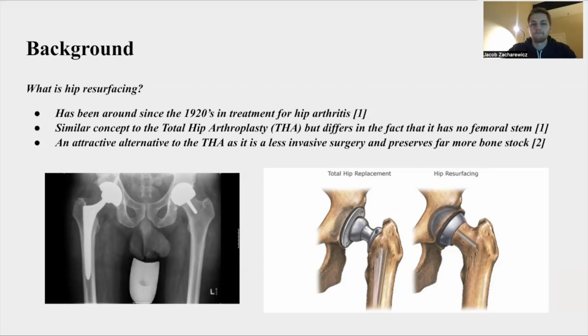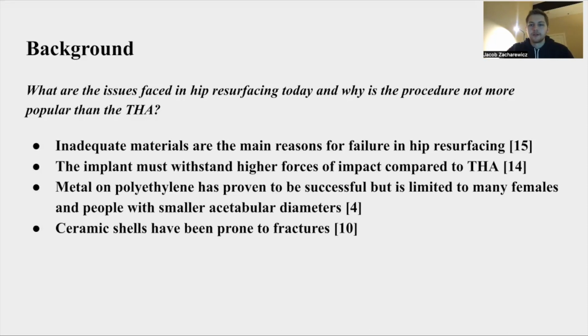and be a very attractive alternative to those in need of a hip implant. Some issues faced in hip resurfacing today, and why the procedure is not more prevalent than a total hip arthroplasty, is mainly due to inadequate materials that can't withstand the high loads that the younger, more active population getting this procedure puts onto the hip and its components. Metal on metal bearings were proven to be successful. However, over time they developed high rates of metallosis, which led to the use of metal on highly cross-linked polyethylene, which is what is mainly used today, but it's limited for many females and people with smaller acetabular diameters.